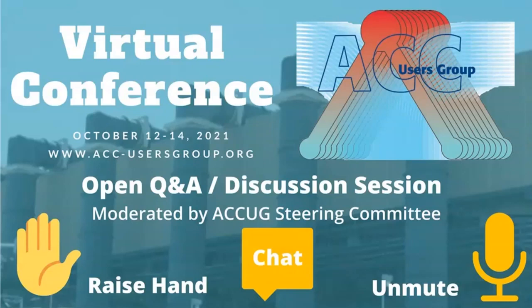So Jeff, I just had one other comment for you. You mentioned at the beginning, in one of your big beginning slides, solid particle erosion. And you probably know that SPE is extremely rare in combined cycle plants, and it's not likely to have come from the air-cooled condenser, because the iron particles are not hard enough. It's more likely to have come from the superheater or reheater. It's interesting, and it very well could have come out of the superheater and reheater, but we were measuring quite a bit of iron coming out of the condenser, and most of the buildup of iron was taking place in the LP drums.